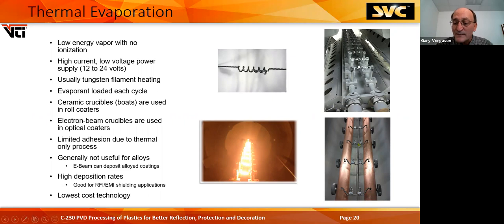There's a couple different types. These are kind of a camel looking filament with coils of aluminum on. And this is kind of what it looks like when you're looking through the window when the process is working. It's high current, low voltage, usually 12 or 24 volts. Tungsten filaments. Evaporant has to be loaded every cycle. Ceramic crucibles are used in roll coaters. Electron beam crucibles are used for the optical industry.